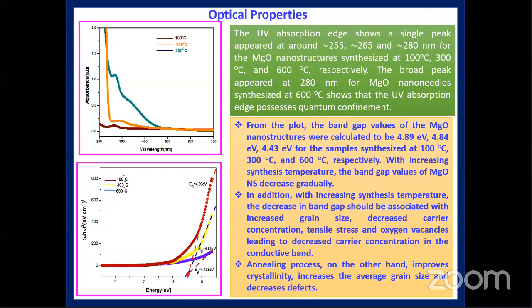And then we calculated the band gap energy for the MgO nanostructure by using the Tauc plot. You can see from the Tauc plot, the band gap energy was calculated to be 4.89 electron volt for 100 degrees Celsius. At a synthesis temperature of 300 degrees Celsius, the band gap is 4.84 electron volt, and at 600 degrees Celsius, 4.43 electron volt. You can see that when the synthesis temperature is increased, the band gap values decrease. The reason is that the band gap is associated with increased grain size, decreased carrier concentration, and tensile stress and oxygen vacancies, leading to a decrease in the carrier concentration in the conduction band.